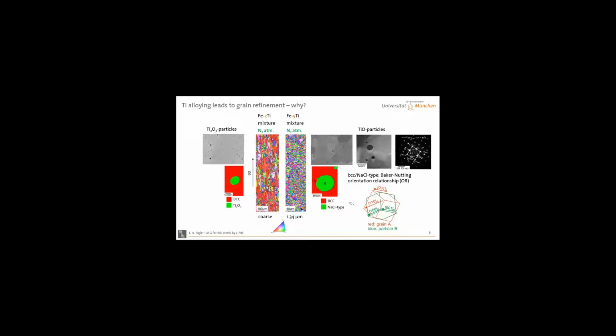I just see that I don't have the scale bars here, but I think it is roughly the same scale bar for the EBSD and for the SEM. I will check that later. So these are all particles that are roughly 100 nanometers in size or less. If we look for a while, we also find some coarser ones, and we pick these coarser ones for an EBSD analysis, and we see, okay, in the case of 2% titanium, we have Ti2O3 crystal structure.